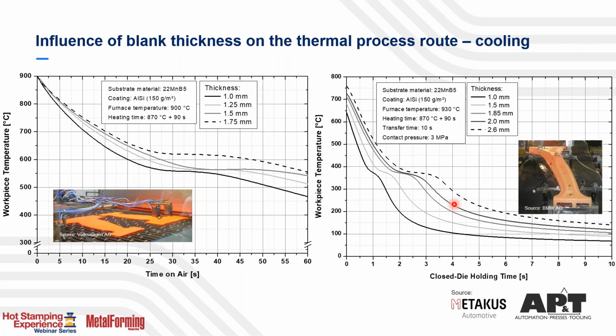Then we have the influence when going after the forming. We had the heating process, we had the quenching process, and now we're going into the cooling process. Different sheet thicknesses when transporting the blank in air, basically. This is prior to the hot stamping, and then in here we have different quench rates for different thicknesses during the quenching process. So you see, depending on which sheet thickness you're using for the final component, you need to calculate with different cooling rates while transporting the blank in air. The same goes for quenching in a die. Of course, higher thickness requires a longer quenching time, close die holding time in the tool.